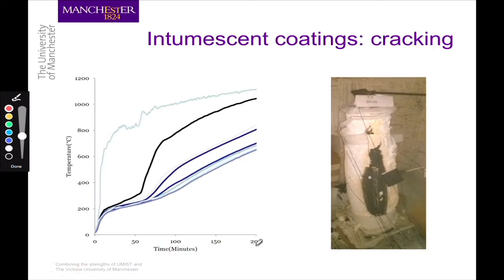Well, for intumescent coatings, one big issue, of course, is that it can crack. At the moment, when we are testing fire protection materials, we take the average temperatures in our calculations, but average temperatures can be misleading. For example, we have tested a piece of tubular steel, and you can see in here the recorded temperatures at various locations around this piece of steel. The temperature in here, which is in this cracked area, is almost reaching the temperature of the fire. This is the fire temperature, and in other places they are quite low. So it is misleading to do the averaging. We really have to understand when a crack happens, how do we deal with that? Using the average is no good. So that's one big challenge.